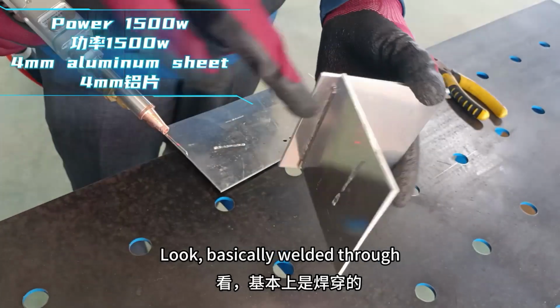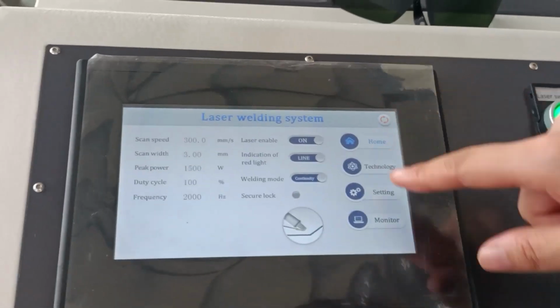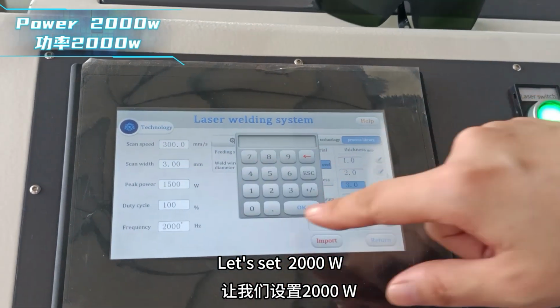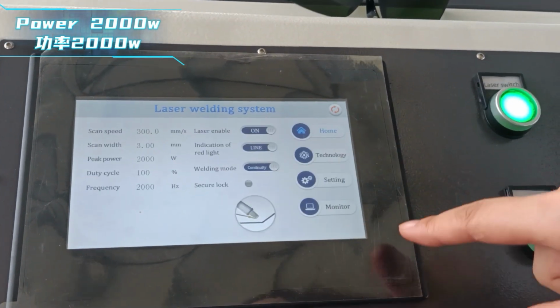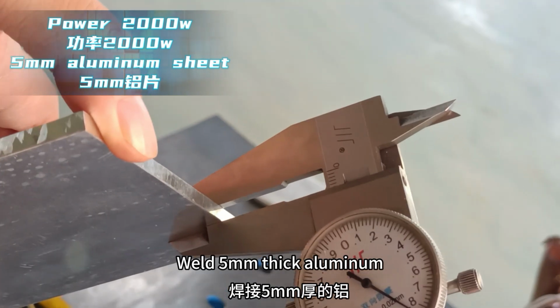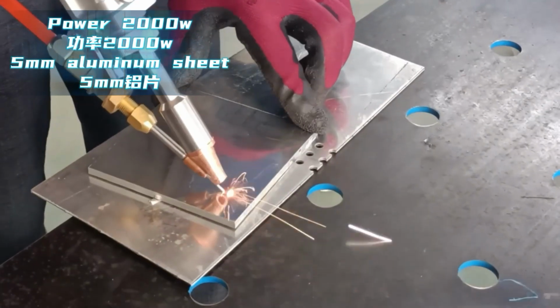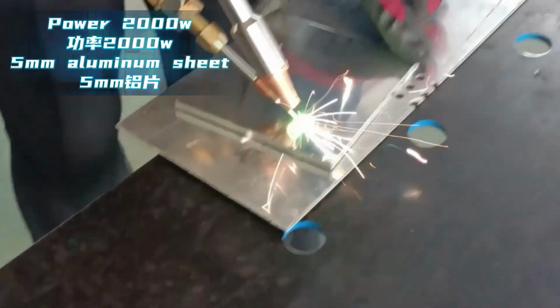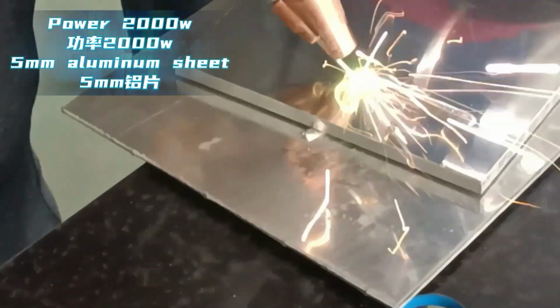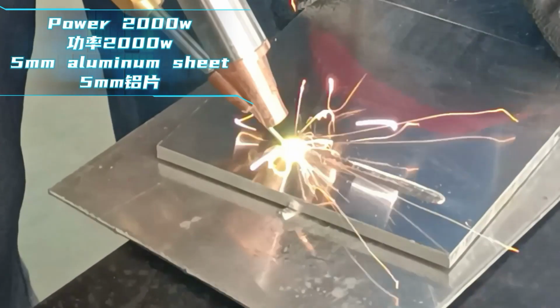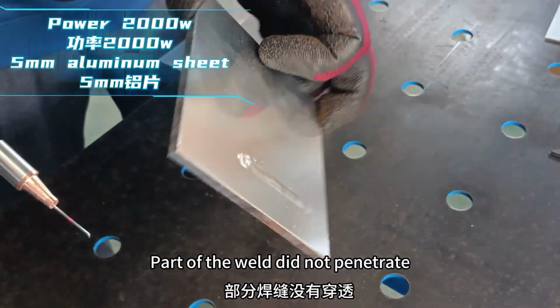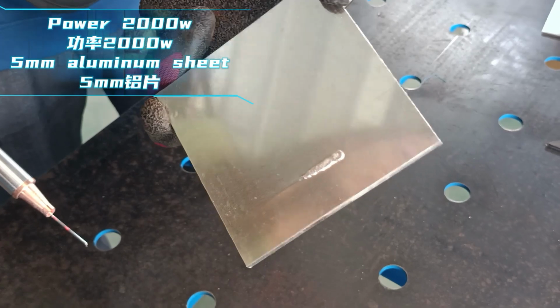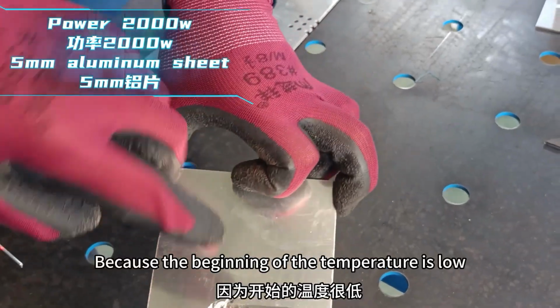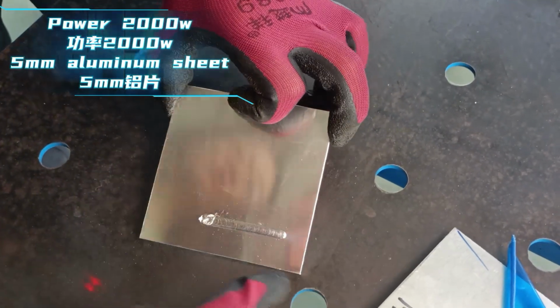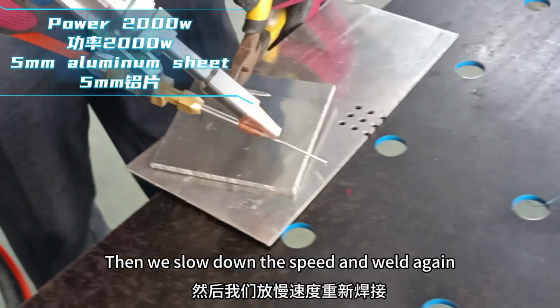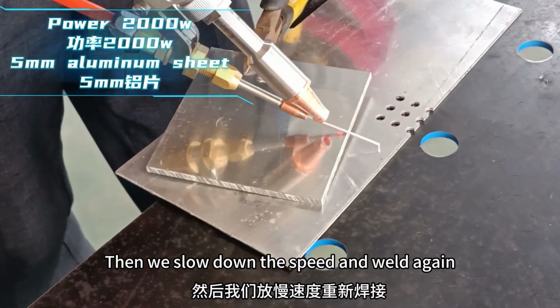Look, basically welded through. Let's set 2000 watts. Weld 5 millimeters thick aluminum. Part of the weld did not penetrate. The master said because the beginning of the temperature is low. Then we slow down the speed and weld again.